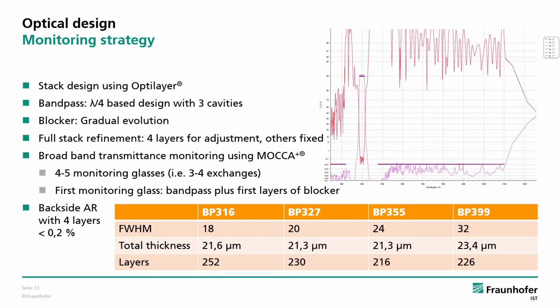Finally, the stacks were put together with most of the layers fixed. Only 4 layers at the connection were used for adjustment. This leads to quite thick coatings with more than 20 micrometers and layer numbers from 216 to 252. For the backside, an anti-reflection coating with less than 0.2% residual reflection was calculated. A stress compensation layer was added. I will come back to this later.